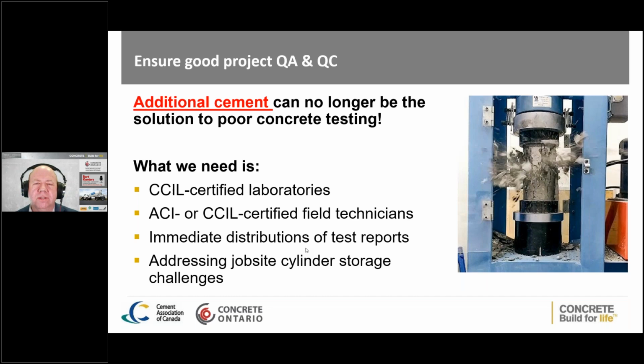So one of the critical issues that we have to address is the over-design that we have in our mixes just to avoid some of the challenges out on the job site. So again, working positively with other associations like the Canadian Council of Independent Laboratories, we need to encourage proper and efficient testing practices out on job sites. If there's challenges for the testers when it comes to providing or obtaining proper cylinder storage conditions, we need to work with them to address that. If we're going to optimize our mix designs, and that's one of the key components that Adam pointed out in his net zero roadmap, we need to reduce the over design in concrete. That needs to be one of the primary things that we look at.